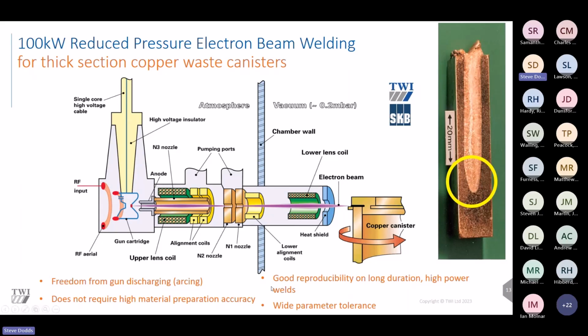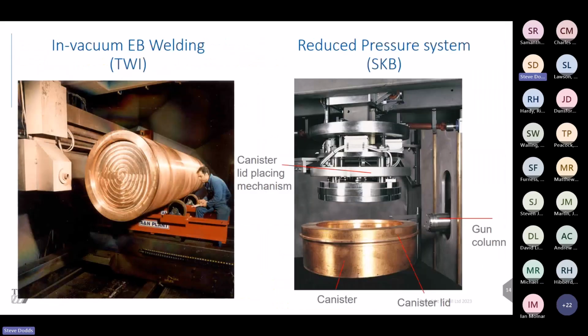There's other benefits as well mentioned at the bottom, but this was specifically targeted as a technology for canister design because of the production environment, because of the weld requirements, and because of the scale of the objects that we were welding. And here's some images of TWI starting to play with some really big stuff in the electron beam chamber. I don't know if you can see my mouse, but this is where the electron beam is emitted, and you roll the part around, and then that was then transferred over to SKB as a reduced pressure system specifically built for their trials.